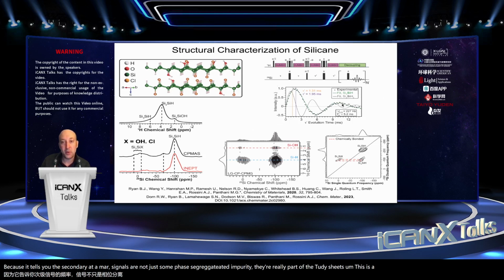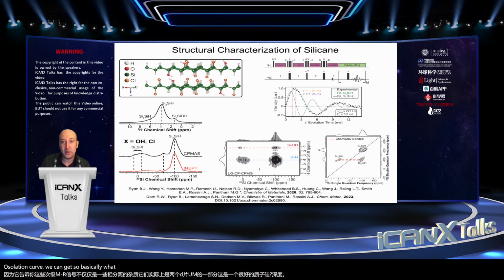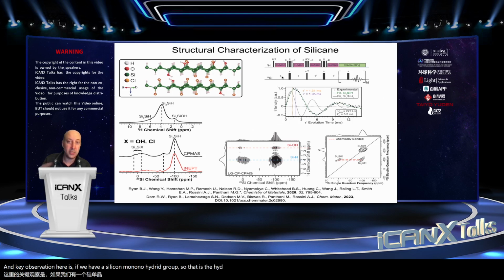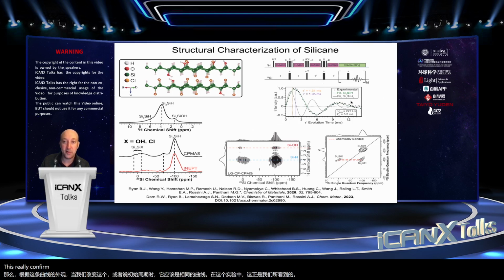This is a nice proton-silicon INEPT oscillation curve we can get. So basically what we do is we vary the mixing times for which we let the J couplings evolve in this INEPT experiment. And the key observation here is if we have a silicon monohydride group, so that is the hydrogen and the silicon are in a one-to-one stoichiometry, then based upon the appearance of this curve, it should be the same curve when we vary this tau or tau prime period in this experiment. And that's exactly what we see. So this really confirms that we have SiH groups in these 2D materials.